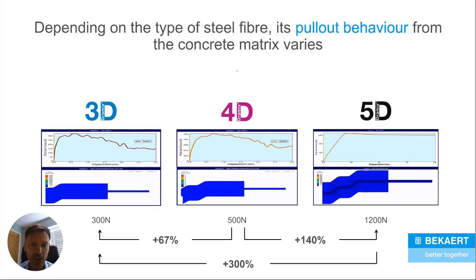Dramix 5D, which has an extra wave on the end, actually works in a completely different way. It is a bit of a one-off in the market. You don't actually see that fibre start to yield in any way until you've applied a force of around 1200 newtons, which is obviously around 4 times that of the Dramix 3D. But the failure mode is different. The anchor is actually 100% efficient, so the anchor will not move. It will remain embedded in the concrete.